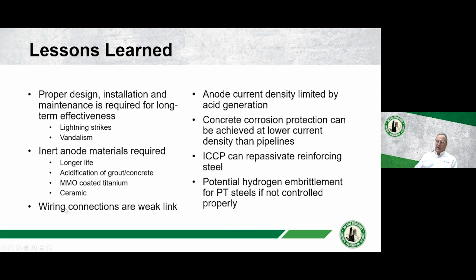The wiring connections have been identified as the weak link. You can have a rectifier that's been shielded and protected from lightning strikes and inside a chain link fence, so it can't be vandalized. But if you make poor wiring connections, that'll shut the system off independently of all the other things. And the anode current density limitation is something that they've identified for the mixed metal oxide. You have 110 milliamps per square foot of mesh surface, and that current density, if you follow that, will not create acid.